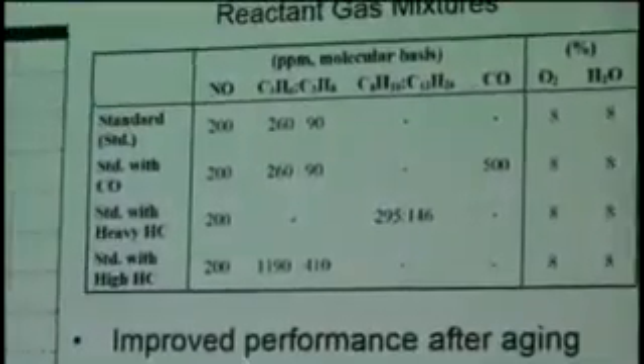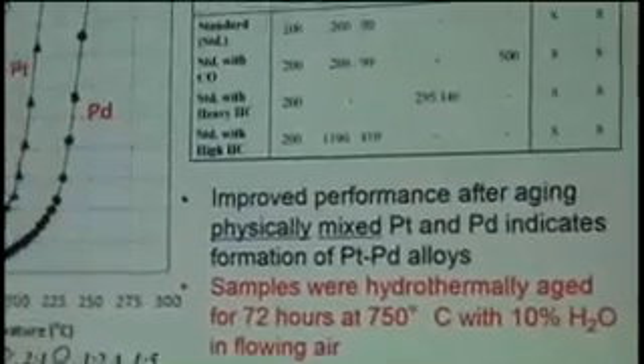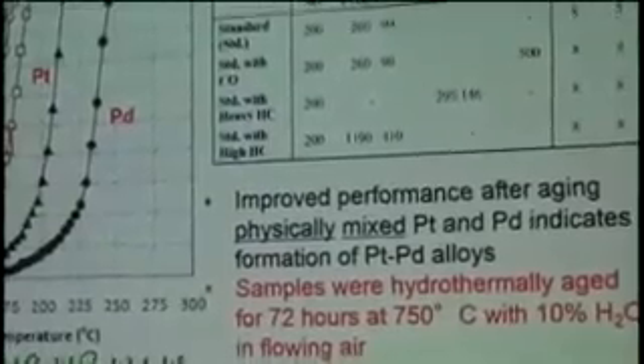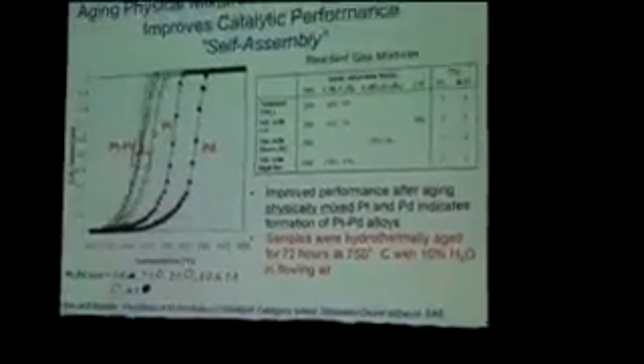Now, palladium is used in these demonstration catalysts. What's remarkable is this light-off curve that I brought from Chan Kim, who used to be at GM, provided on this project. What it shows is that the platinum light-off is not at as low a temperature as the platinum-palladium light-off. So the first thing you learn is that platinum-palladium catalysis is good from the catalytic standpoint. What's more remarkable is that in this case, the two catalysts were physically mixed. They made platinum on alumina and palladium on alumina, they just mixed them and aged them at 750 C.